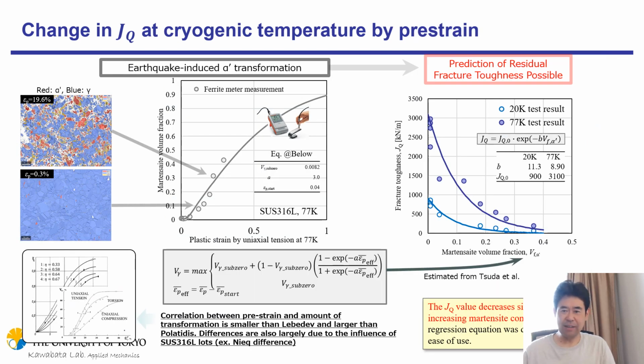Of course, pre-straining leads to a lot of martensite transformation, so the pre-straining amount can be converted to martensitic transformation volume fraction. Now we got the JQ value degradation curve, this graph, not only at 77K but also 20K. We carried out the 20K experiment using a cooling bath filled with liquefied hydrogen. This curve will bring the future judgment whether we can continuously use the storage tank even after a huge earthquake, by measuring martensite amount point by point.